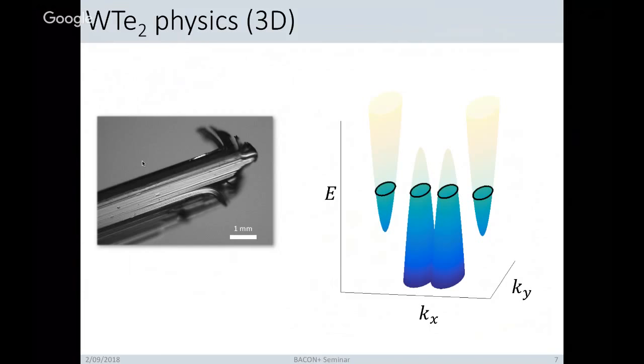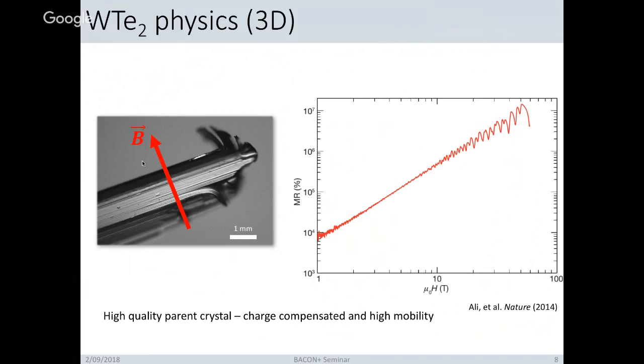Quite evidently, we have all sorts of measurements that confirm that you pretty much have two hole pockets and two electron pockets of equal density. One of the consequences of a semi-metallic state is you expect a large magnetoresistance, which is dependent on the crystal quality and on the doping level. And what was found in this groundbreaking work that sort of introduced this material back to our world is that if you apply a large magnetic field perpendicular to the planes and investigate the magnetoresistance, you see here's the percentage change in resistance as a function of field, and we get this quadratic behavior, it's a log-log plot, quadratic behavior all the way up to almost 60 Tesla and a 10 million percent change. And in fact this has even been improved upon as crystals have gotten more pure. This has already opened up a field of extreme magnetoresistance phenomena in 3D crystals, but what's great for our lab is that we know from these sorts of measurements and other investigations that the parent crystals are very high quality.